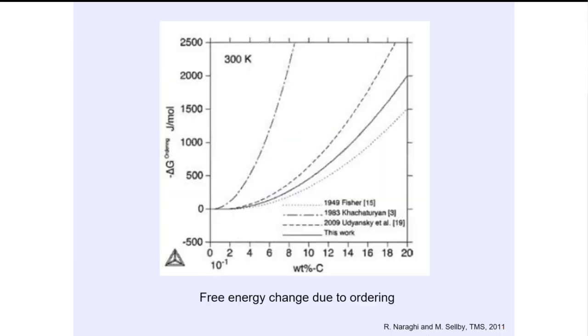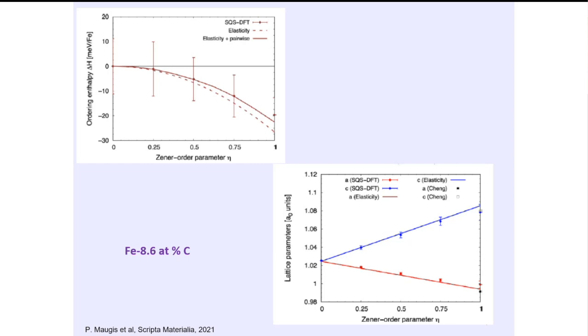There are models which calculate the free energy, and one can see that if the carbon is high, there is an advantage in terms of free energy when the tetragonal structure is formed. Very recent first-principles calculations also show that as carbon atoms order on one of the sub-lattices, it is favored by enthalpy change. So enthalpy change is favorable when carbon atoms order on one of the three sub-lattices.